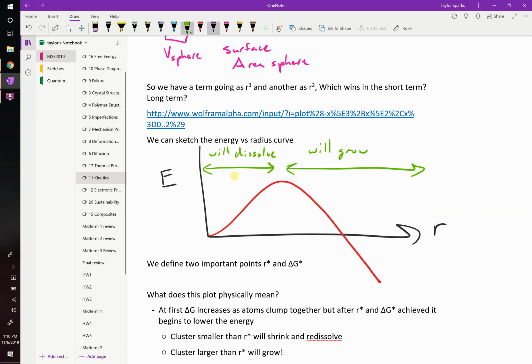Okay? We can quantify the energy barrier. We can say that this barrier right here is an activation energy needed for what we're going to call nucleation. We're nucleating a secondary phase. That little nucleus, this is the nucleation barrier. So that's delta G star. And the point at which you observe delta G star is R star. Those are the two important points to take away from this.